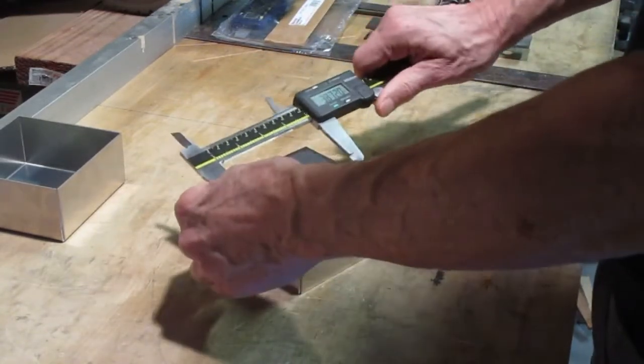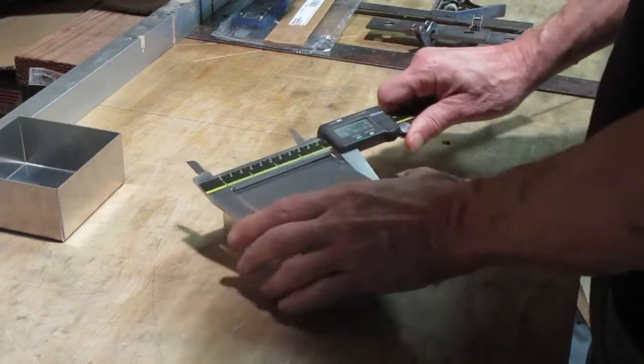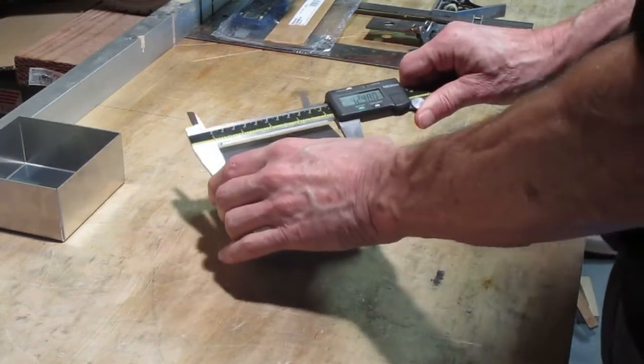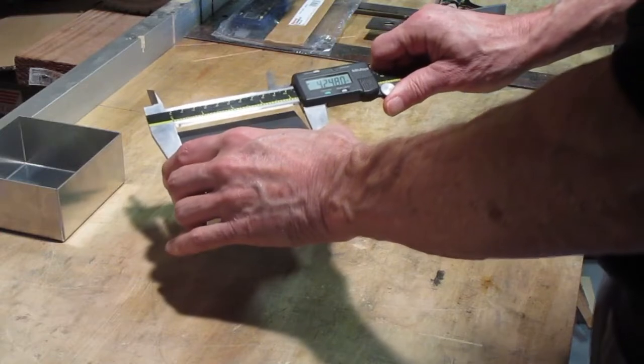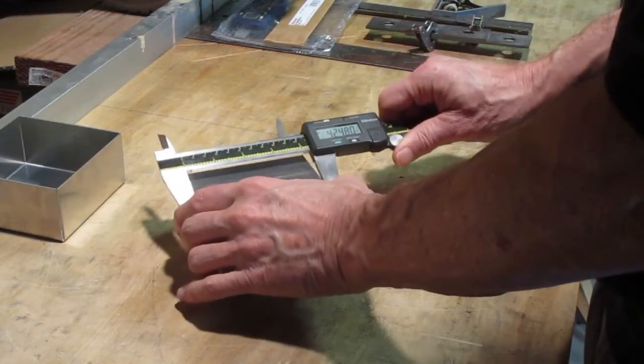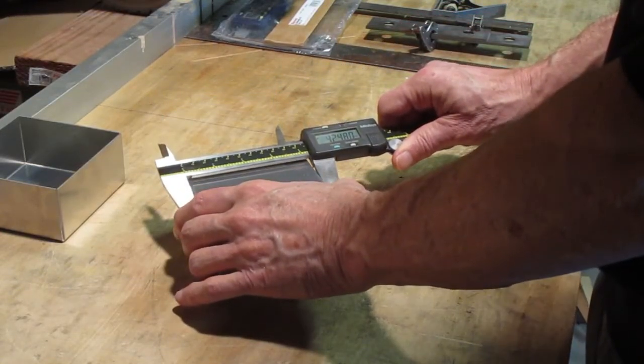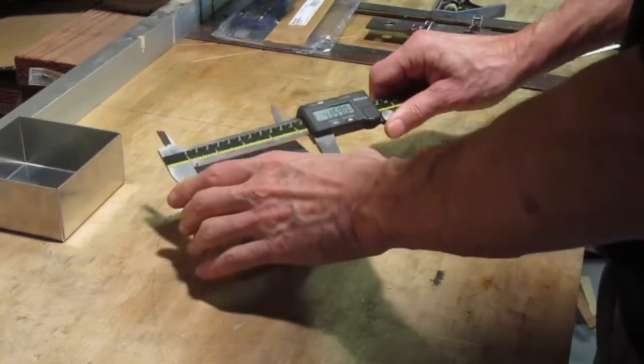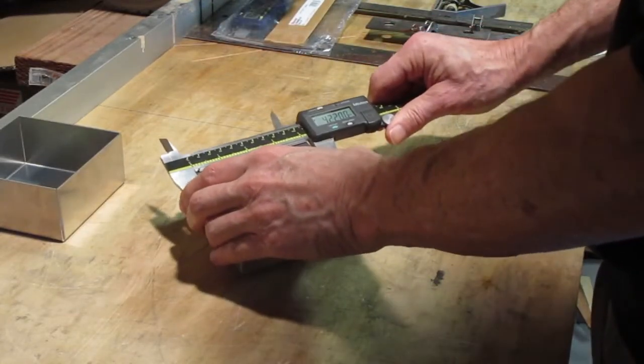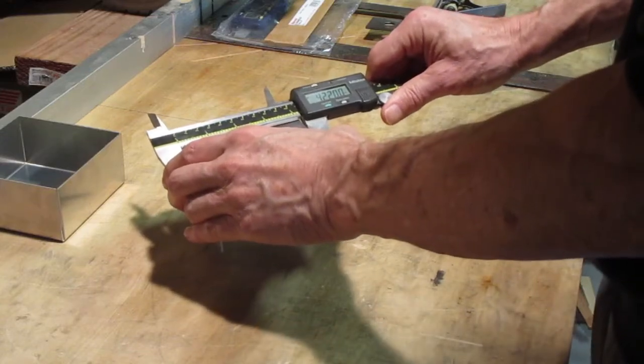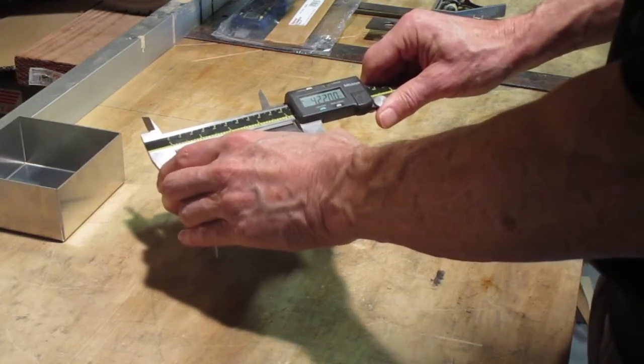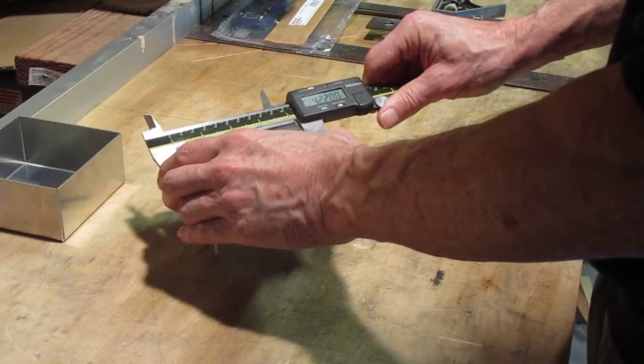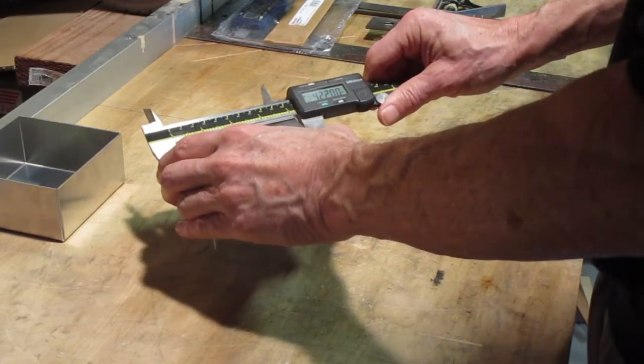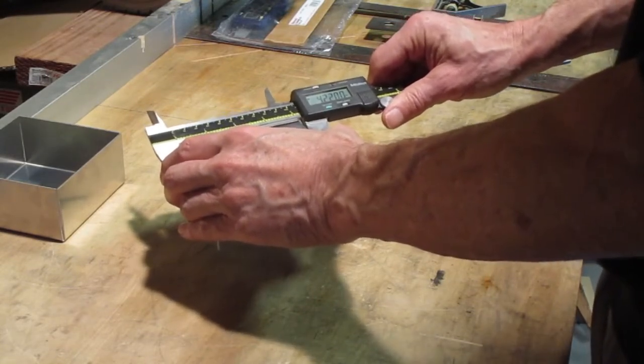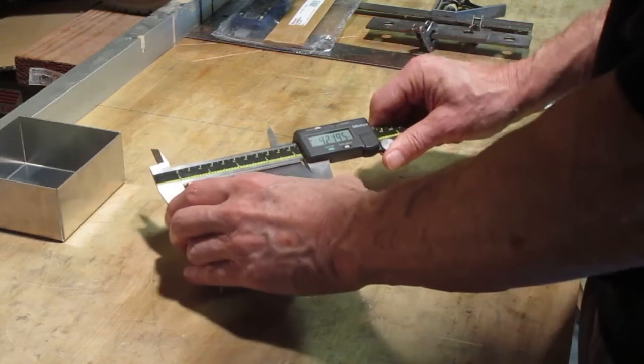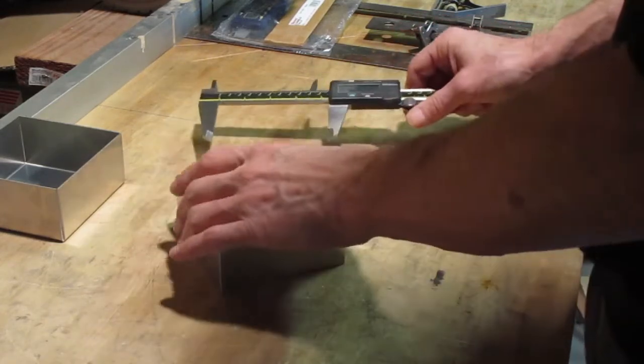So let's see what we got going on here. This is 2 thousandths shy. It's 4.248, which is pretty good considering how we did this. This one here is going to be short, and this one measures 4.220. So if we add 25 thousandths to that, that would put us at 4.245, or about 5 thousandths short, which across 2 bends is pretty good.